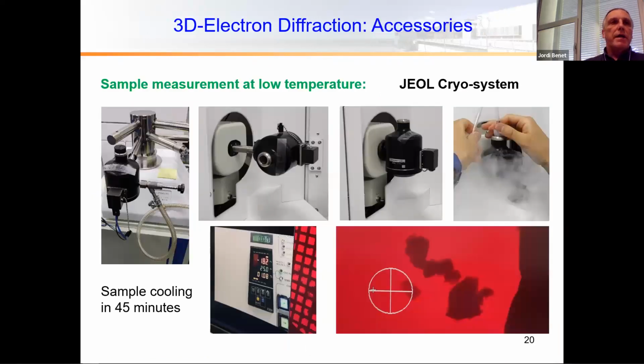An important point, and we have this system here in Tarragona, is to cool down crystals, and for this we use a JEOL cryo system. In this case, you can put the sample at room temperature inside the system and then cool down to 90 or 100 Kelvin using liquid nitrogen.